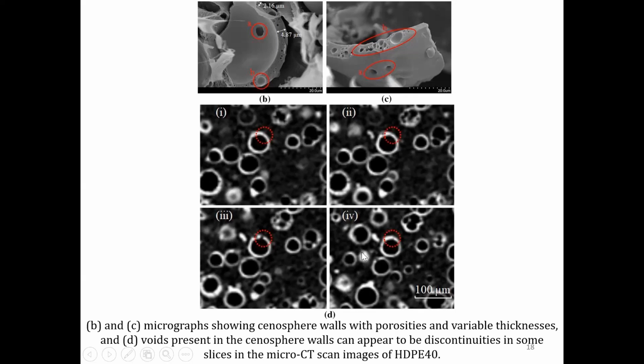Now, where the interpretation goes wrong is, if we focus on this microballoon, it seems very intact here. Now you can see a small discontinuity here. The discontinuity has completely grown here, and again the discontinuity closes here. So by looking at the micro CT, you may say that this microballoon is cracked, failed, fractured, but it is never so. The reason is these inbuilt porosities which open up and close as you slice this microballoon in the micro CT. So please make a note of this. Whenever you do micro CT, you may come across such observations. That does not mean the system has failed or the microballoon has fractured. It might be that there is some discontinuity inbuilt in the reinforcement, which you need to look at and compare with other slices.